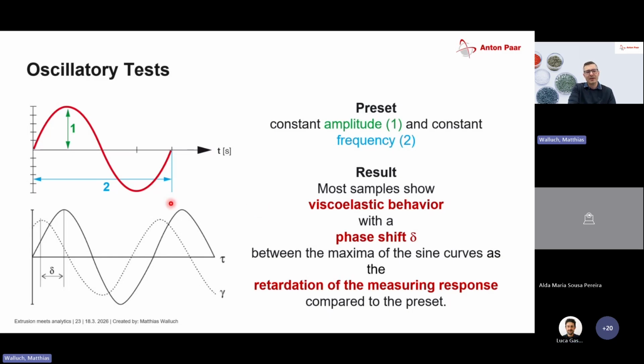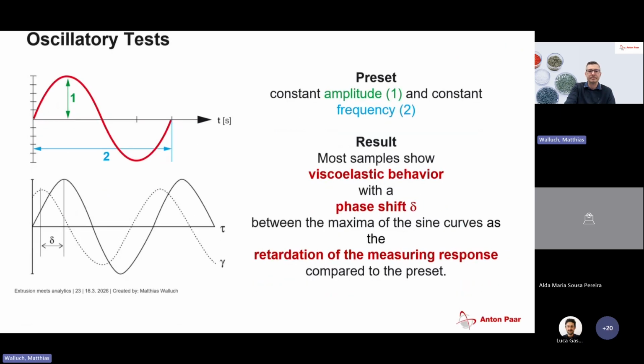So like we see here, this is what we apply, a stress or a strain, and this is what we get back. So we measure stress or strain, and we measure the other one, so the one that is not applied. And what we can see here is that there is a certain phase shift. This phase shift is correlated to the viscoelastic properties of a material. If we would have a completely solid material, a completely elastic material, there would not be a phase shift. If we have something water-like, there would be a phase shift of around 90 degrees.